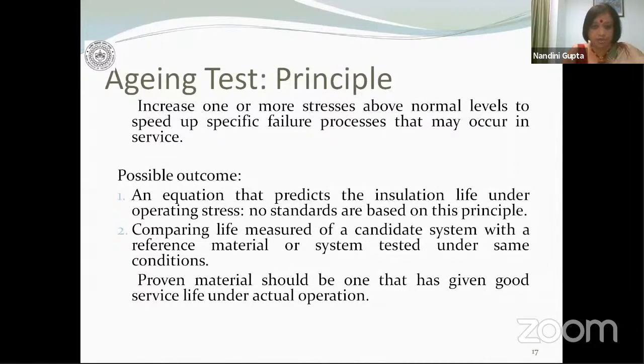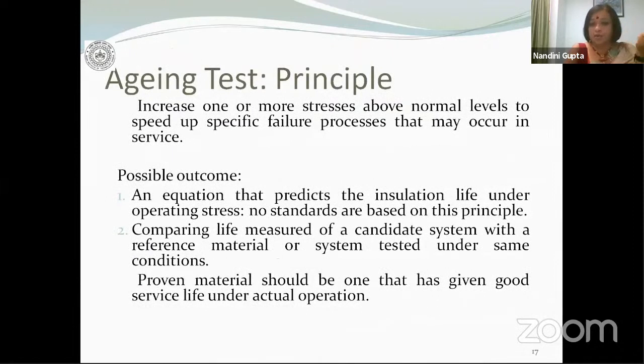based on this principle. So the idea is a little less ambitious, in the sense that what you will do is you will work with a candidate system. So let's say you have devised a new material. For example, sometimes we put nanofillers into conventional epoxy resin. And epoxy resin has been in service, and not just in laboratory test, it has been in field, not just in case of accelerated aging, but in normal tests, we have used epoxy resin.